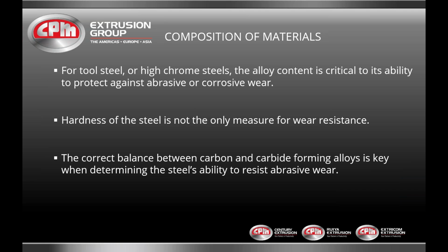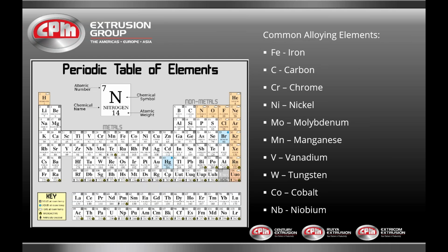We'll be discussing the composition of materials now. For the tool steels or high chrome steels, the alloy content is critical to its ability to provide abrasive or corrosive wear resistance. Hardness isn't the only measure of the ability to provide wear resistance, though. The balance between the carbon and the carbide forming alloys is key when determining the steel's ability to resist abrasive wear. Some of the common alloying elements are iron, carbon, chrome, nickel, molybdenum, manganese, vanadium, tungsten, cobalt, and niobium.